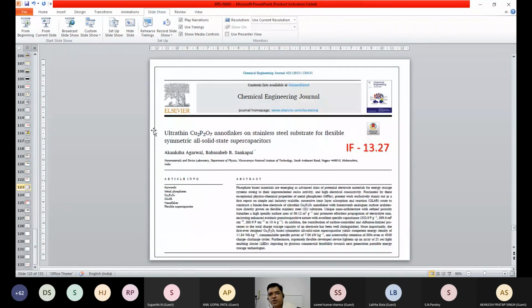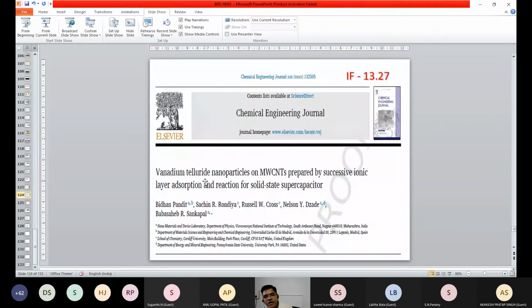Just this year we got very good publications in terms of higher impact. One paper, on cobalt phosphate on stainless steel, is published in the Chemical Engineering Journal, a very high impact factor journal with impact more than 13. Recently, we made vanadium telluride on the carbon nanotube by simple successive ionic layer adsorption and reaction. Not only supercapacitor, but we have also done DFT studies with the help of our collaborator from UK. This is also published in a journal with impact factor more than 13.